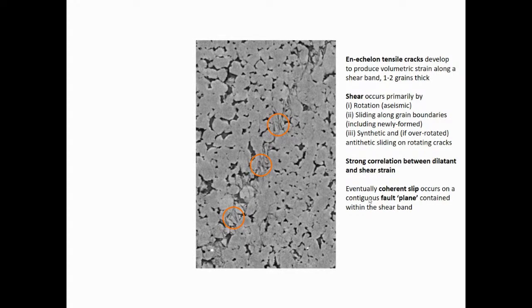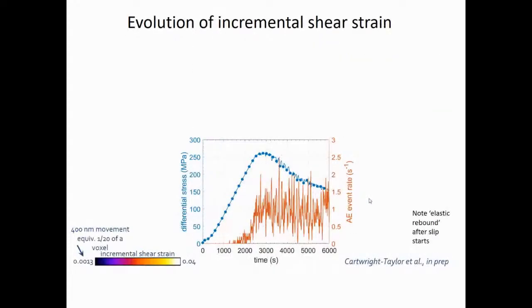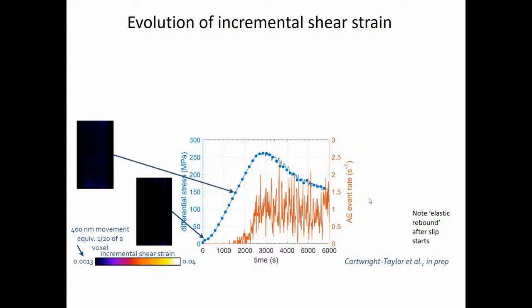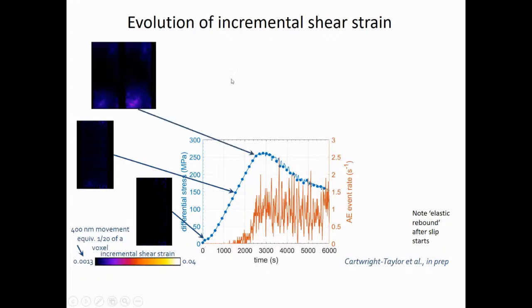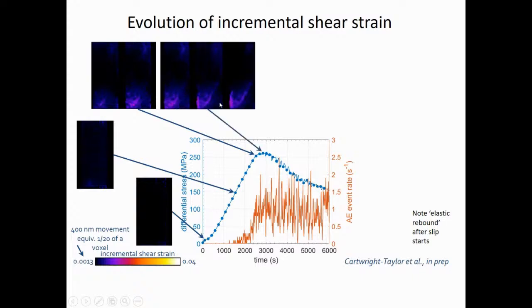Just one last time. Yeah. So these are now the digital image correlations showing the strain. It starts off with no strain, so it's all black, and then you start to see a low amount of strain. Here's the key here. This is a shear strain as an example. And then you can see by the time you get yield, you're starting to see localization. You still have this random deformation that was inferred from the AE and Dave Lockner's experiments. And now you're starting to get more localization as you get to peak stress.